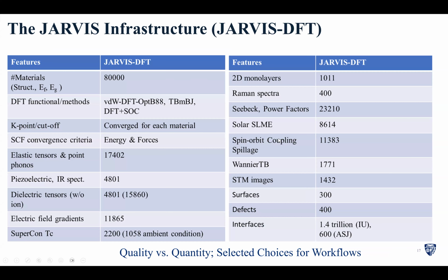In Jarvis DFT, we have a diverse amount of data. For instance, we have about 80,000 materials, unlike many other databases which just have something like a PBE exchange correlation. We have an improved van der Waals functional. Most of the databases you might know severely underestimate the electronic band gap, which makes them unreliable. So we take effort to use meta-GGAs to improve those band gap predictions, spin orbit coupling interaction.